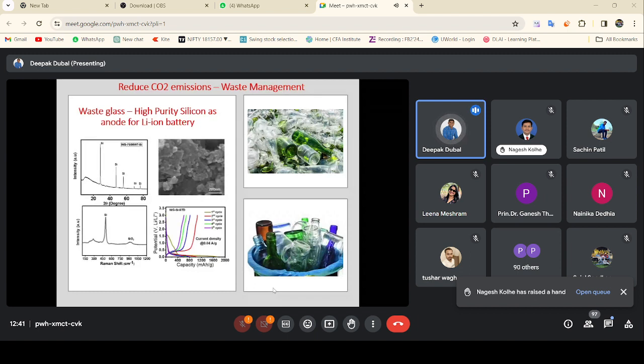Glass is basically silicon oxide. One of our visiting students wanted to try this, and he tried to convert the silicon oxide, which is a glass waste, into highly crystalline silicon. You can see here the X-ray diffraction, where you can see the highly crystalline silicon. All the processes which we have done so far are single-step processes, and we get very high quality, pure materials which can go into lithium-ion batteries.